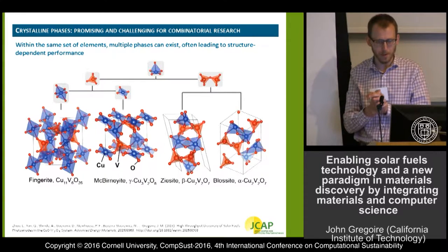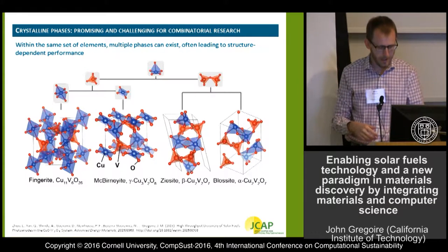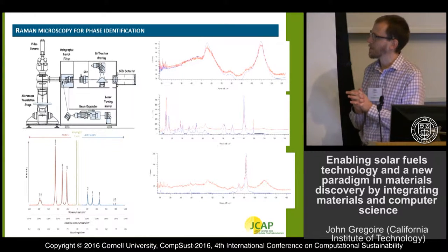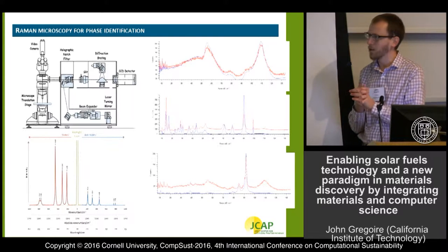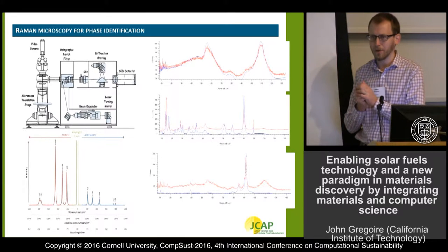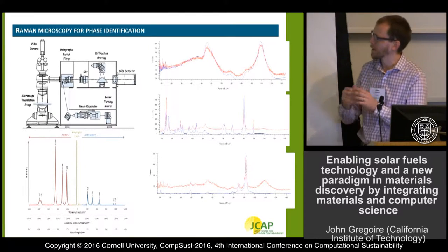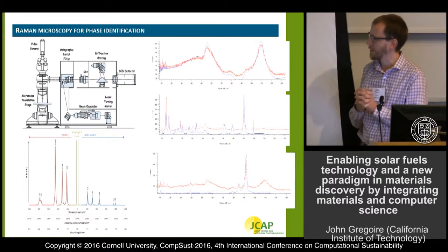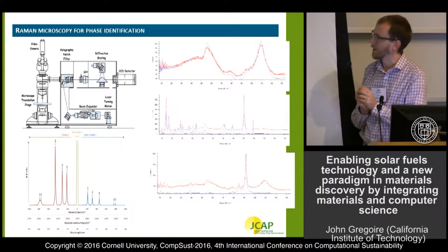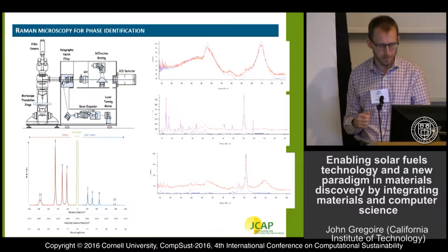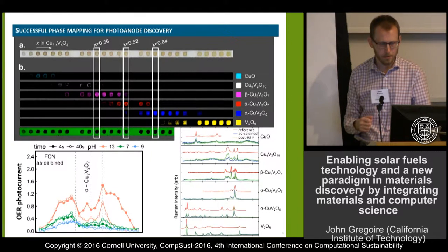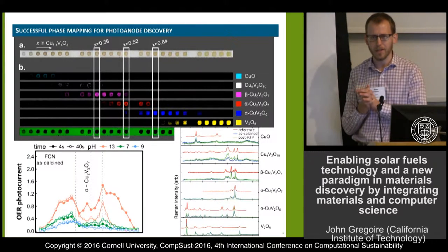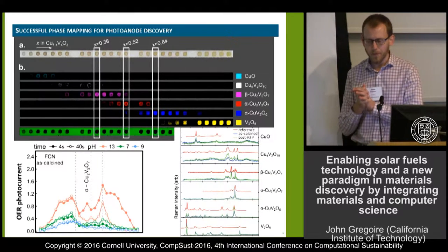I wanted to show in this talk a new experiment we're doing that creates a complementary type of data: Raman spectroscopy. In Raman spectroscopy, you shine a laser on the material; the laser light interacts with the material and releases a spectrum which we detect, and that spectrum can be a fingerprint for a given crystal structure. It's a 1D data set where you get different peaks as a function of the shift of the laser light. We have a brand-new tool from the Renishaw company that uses novel optics techniques so that we can collect this data very fast — on the order of 10,000 spectra per minute.